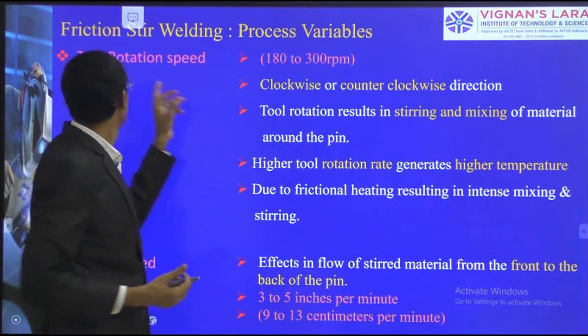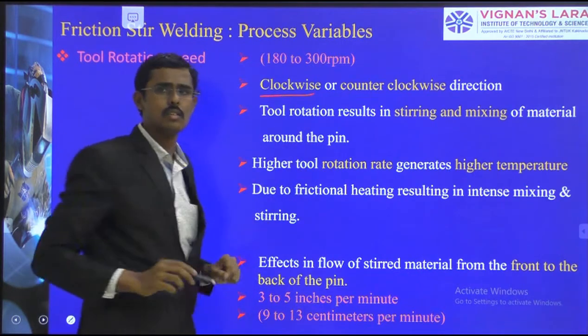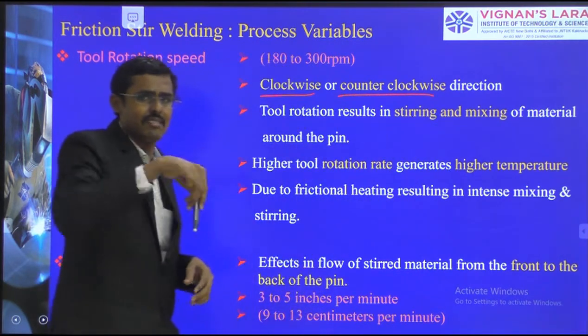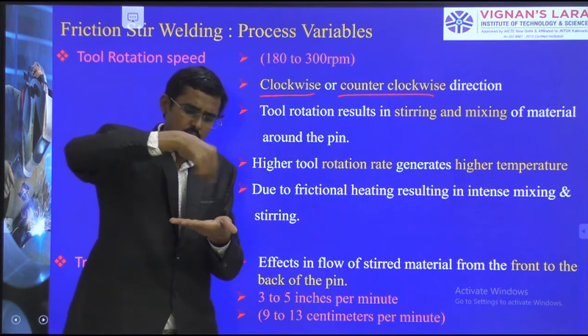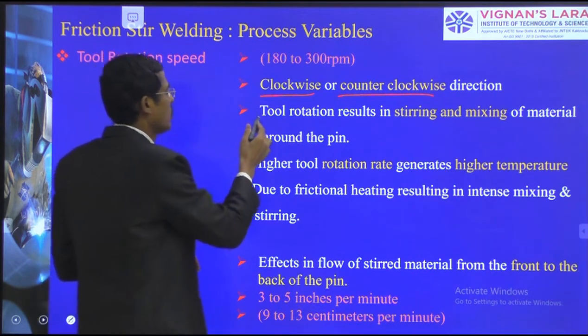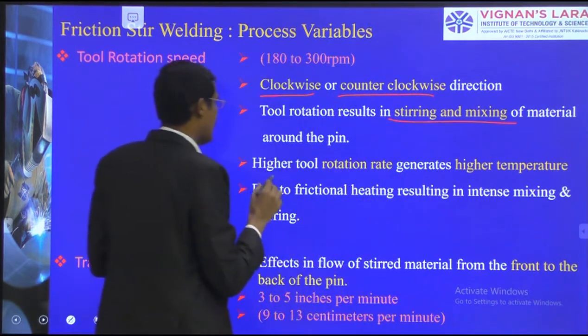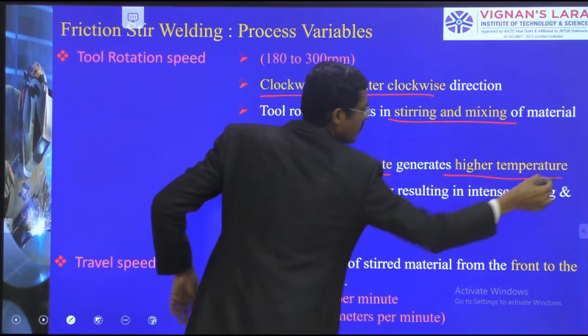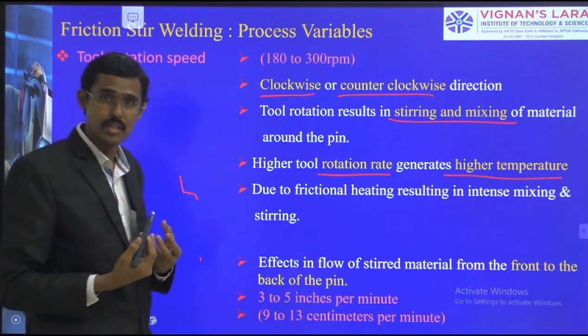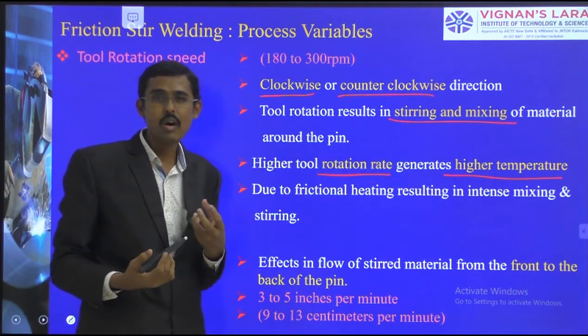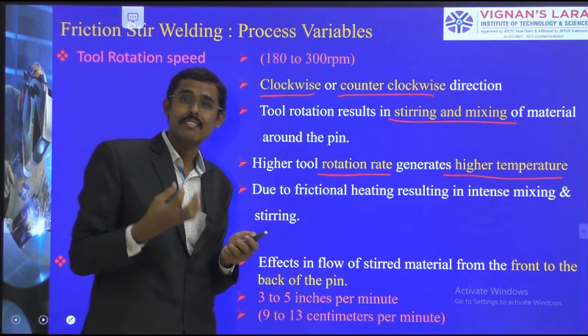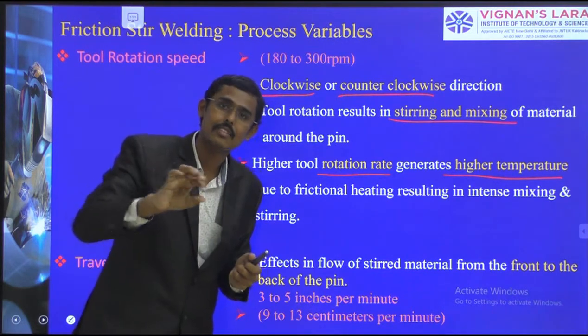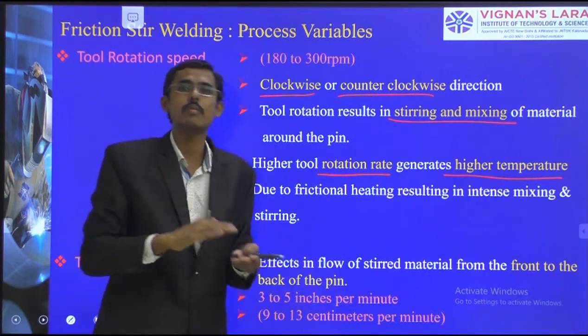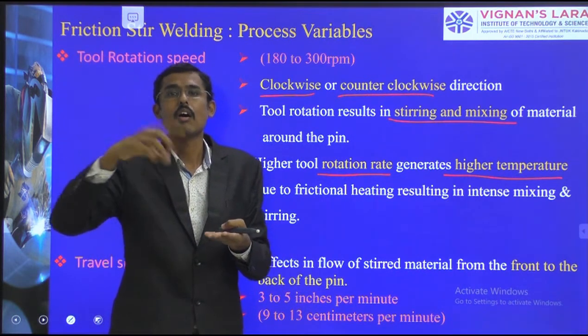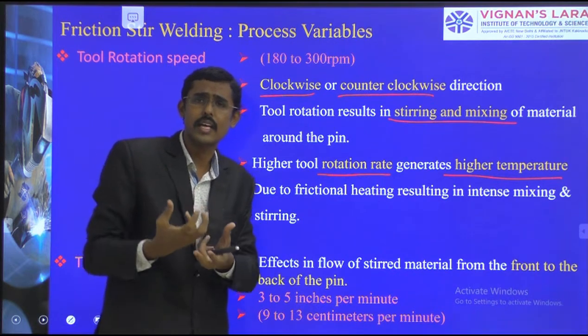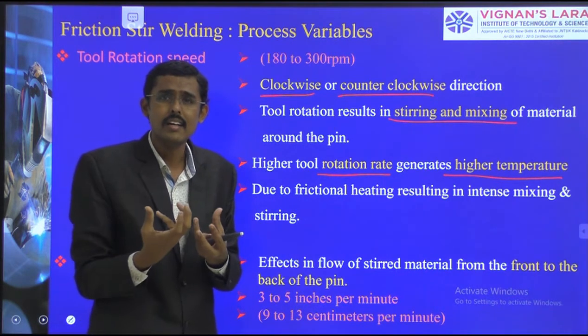So this tool rotation may be clockwise or counterclockwise, any direction. Whether I am rotating in this direction moving forward or in that direction moving forward, whatever it is, the idea is the same. Tool rotation results in stirring and mixing. Higher tool rotation generates higher temperature. The tool should rotate at high speed, then it generates high temperature. Then what should we do? The tool should be selected to have a higher temperature resistance than the material that we are going to weld. If aluminum is going to be welded, we should take steel or titanium, carbide, some hardened material.